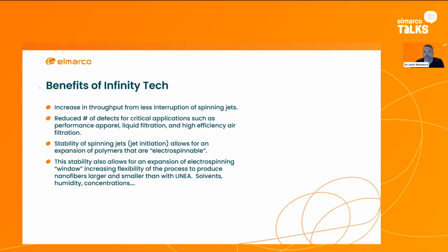So again, benefits: we increase the throughput of non-interrupting jets. Just to sum it up, reducing the number of defects for these critical applications. It helps with the stability of the spinning jets, which also helps us with making some polymers actually electrospinnable, we would say. And then we also see an expansion of the electrospinning window, as I described, where you can use some different solvents, polymers, and concentrations to see if you can make larger or smaller fiber diameter than you probably can reach otherwise with a standard Linea technology.